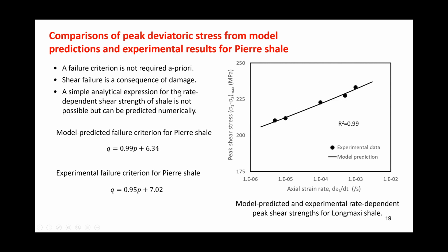I cannot derive a simple analytical model for the shear strength, but we can predict it numerically. This is the model predicted shear failure surface. This is the experimental. And here's a comparison of the experimental and the predicted failure surface. And again, the predictions of the failure surface are excellent, good predictions.